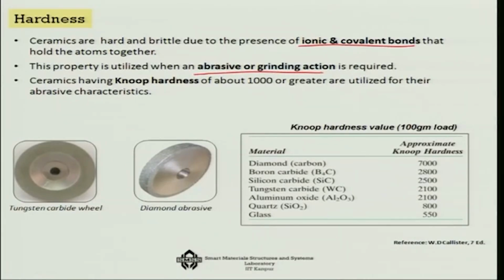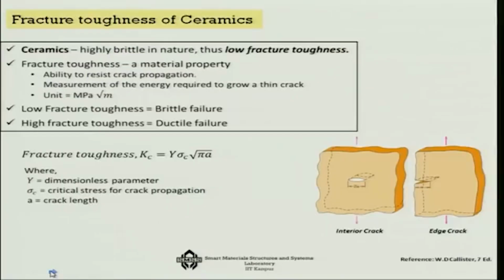Ceramics having a Knoop hardness of about 1000 or greater are utilized generally for their abrasive characteristics. Suppose this one is a tungsten carbide wheel or diamond abrasives, these are generally used, and you can use them for actually sharpening metals. And their Knoop hardness, if you look at it, diamond is about 7000, boron carbide 2800, and anything greater than 1000, that means up to alumina, you can actually use for abrasive or grinding purposes.